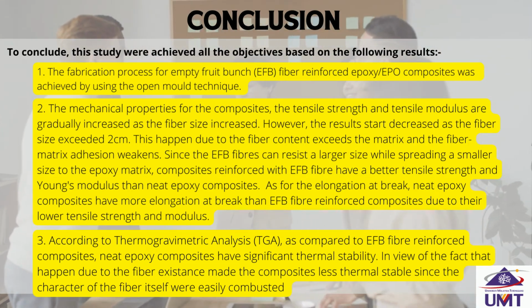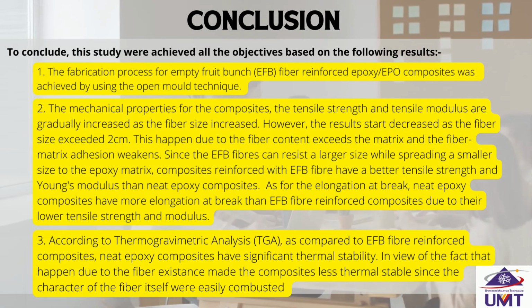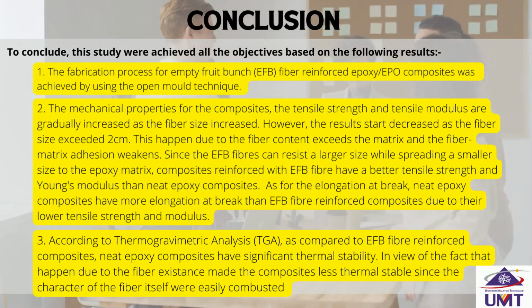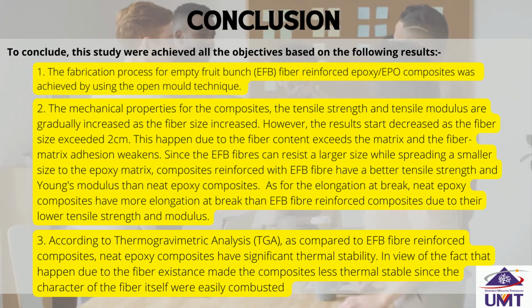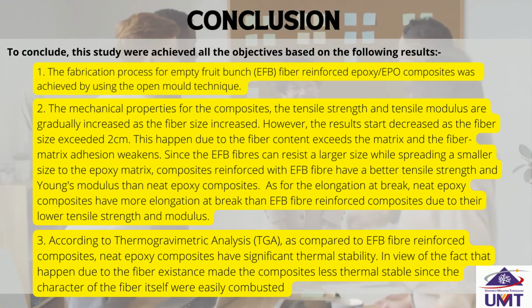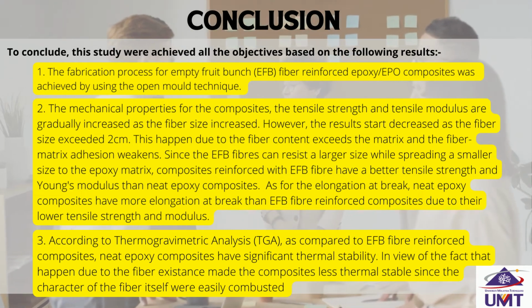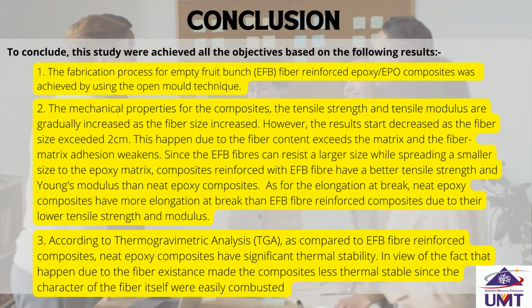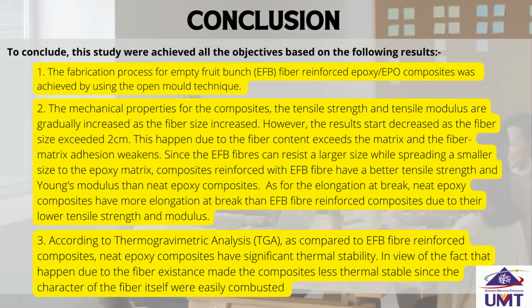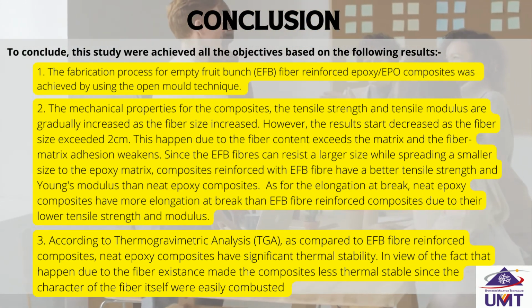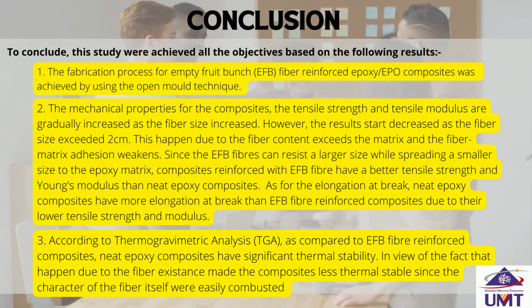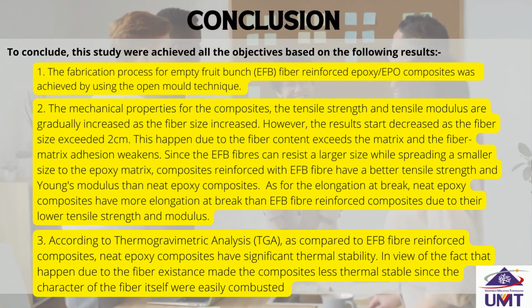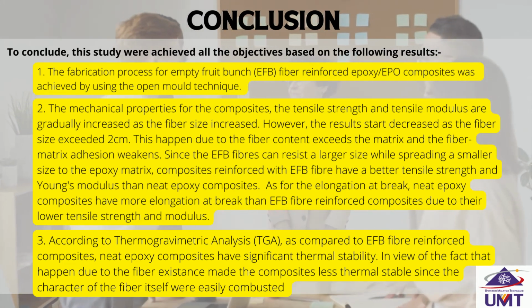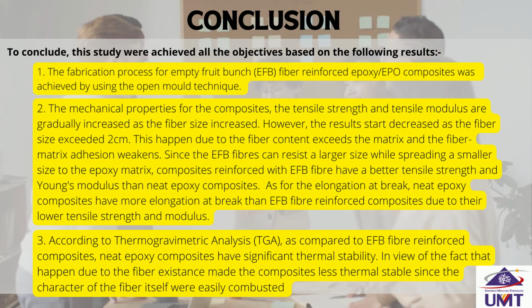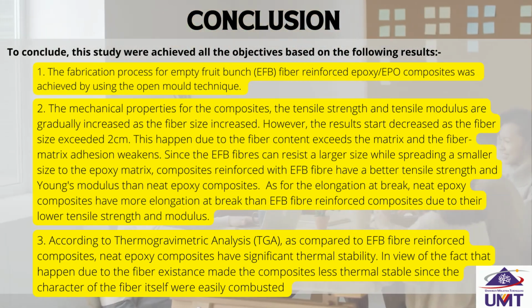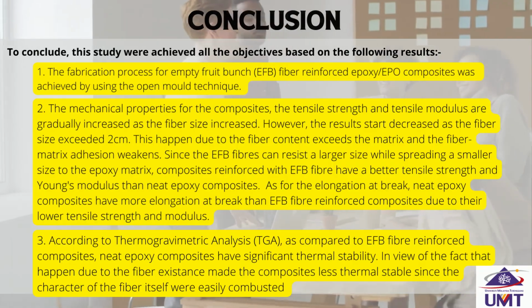Since the EFB fibers can resist a larger size while spreading a smaller size to the epoxy matrix, composites reinforced with EFB fiber have a better tensile strength and Young's modulus than the neat epoxy composites. As for the elongation at break, neat epoxy composites have more elongation at break than the EFB fiber reinforced composites due to their lower tensile strength and modulus. Third, according to thermogravimetric analysis (TGA), as compared to EFB fiber reinforced composites, neat epoxy composites have significant thermal stability. This happened because the fiber made the composite less thermally stable, since the character of the fiber itself is easily combusted.